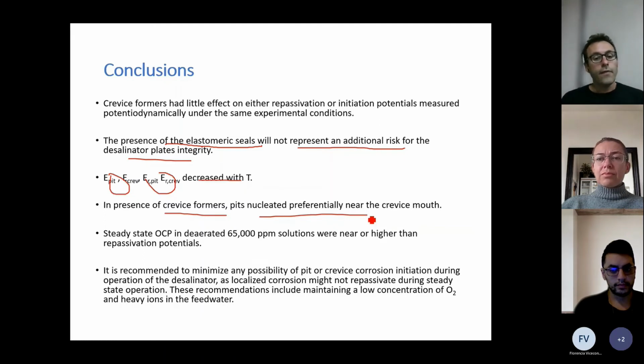So our recommendation is to minimize any possibility of pit or crevice corrosion initiation during operation of the desalinator, because localized corrosion might not repassivate during steady state operation. So essentially, take a close look at the presence of heavy ions in the feed water of the desalinator, and also maintain a very low concentration of oxygen. So I think those are the major points, the highlights of this investigation.